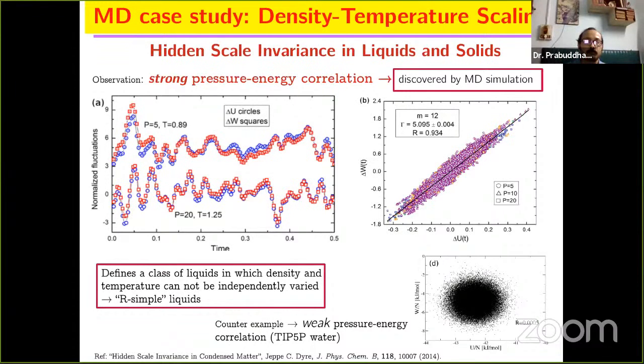As a consequence, you can also show that temperature and density are not independent parameters, so the state space, the phase diagram, is one-dimensional. The partition function does not depend on density and temperature separately, but on a particular combination, rho to the power gamma over T, where gamma is some exponent. So the partition function is a function of rho to the power gamma over T. Rho is density, T is temperature. This is called the density-temperature scaling of IPL liquids.